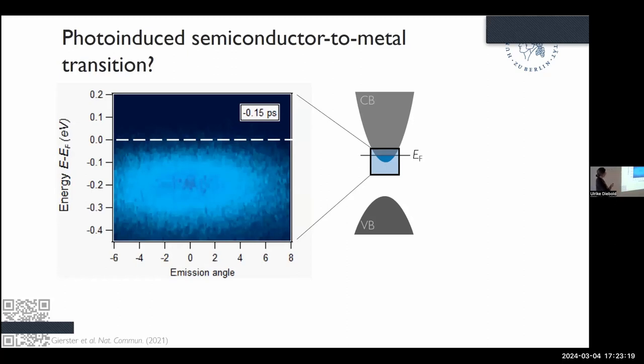This is also photoelectron intensity in false colors, again, as a function of energy. This is the Fermi energy. This is the state that I just showed you, but as a function of emission angle. And you see it has a flat dispersion. It's a localized state. It's the defect exciton state. So this is before our pump laser pulse comes. And now I start the movie, which hopefully works.